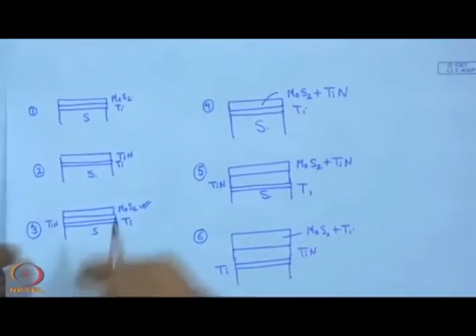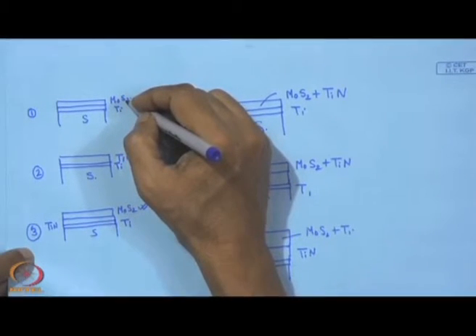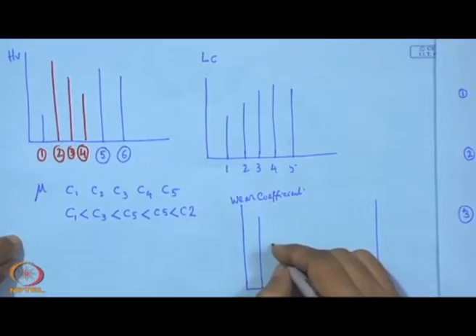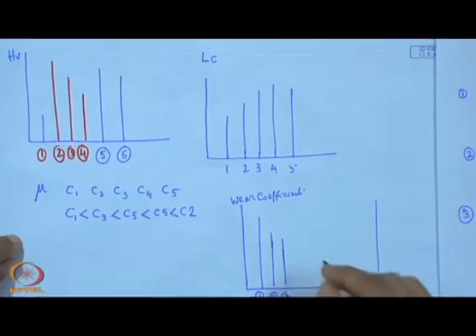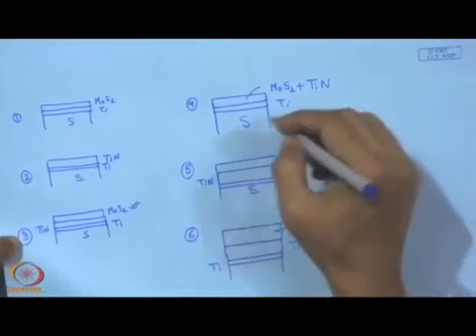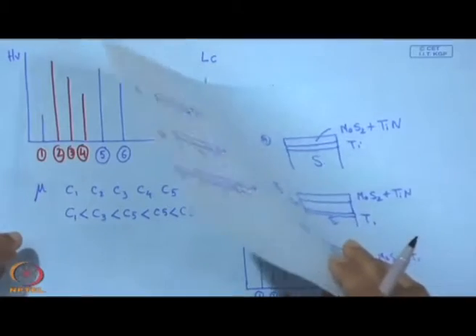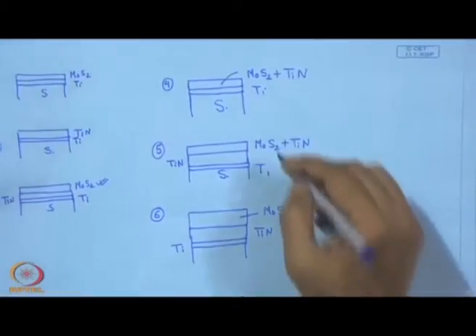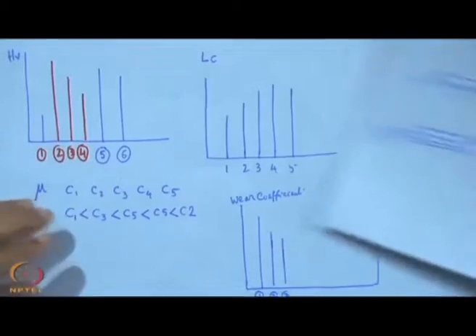So, here we find that the wear coefficient of coating number 1 is not that wear resisting, though the friction value is quite low, but only for a small period of time. And then we have 1, 2, 3, and then we have 4. Number 4 is a composite coating without any support. And finally we have 5, which is a composite coating with a support of titanium nitride, and that also gives quite a low value.